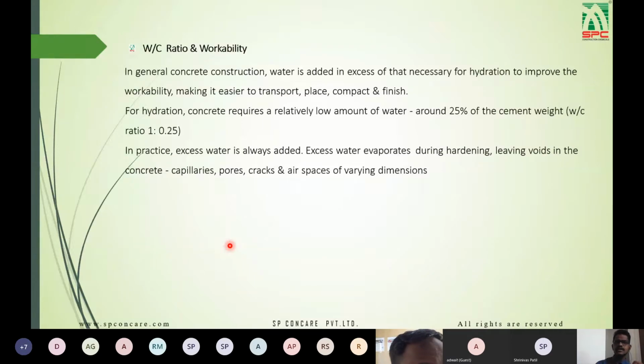But in general concrete construction, water is added in excess of that necessary for hydration to improve the workability, making it easier to transport, place, compact and finish. But when the excess water is added, it evaporates during hardening, which leaves voids in the concrete: capillaries, pores, cracks, and air spaces of varying dimensions.